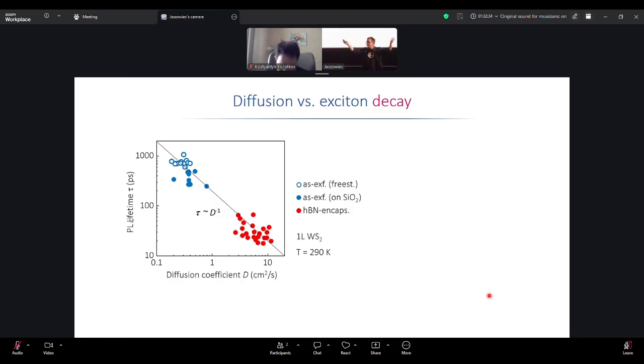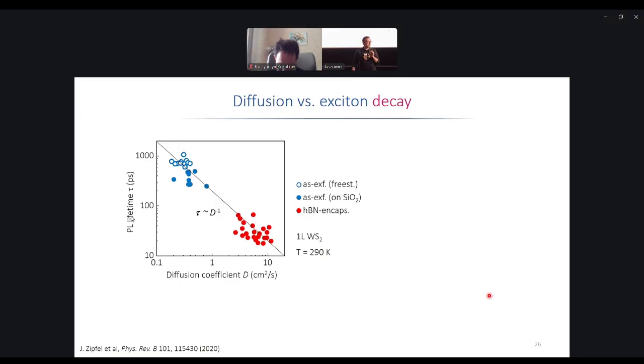Defects, yes, defects. Materials usually have enough defects, there are non-radiative recombination centers in most materials. You can grow very clean materials, but in the majority of cases, there's somewhere a non-radiative state, right? So somewhere an atom is missing, it's a vacancy, and if I propagate towards this vacancy, I will recombine non-radiatively.